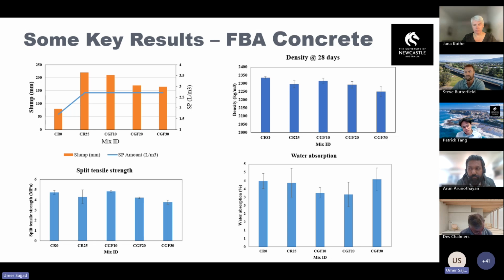And in this test also, you can see that 10% usage of furnace bottom ash provided slightly higher splitting tensile strength compared to the other mixes, and the strength is comparable to the controlled concrete. So in terms of technicality, we don't have much difference between controlled concrete and the concrete using furnace bottom ash as 25% natural sand replacement and 10% cement replacement.